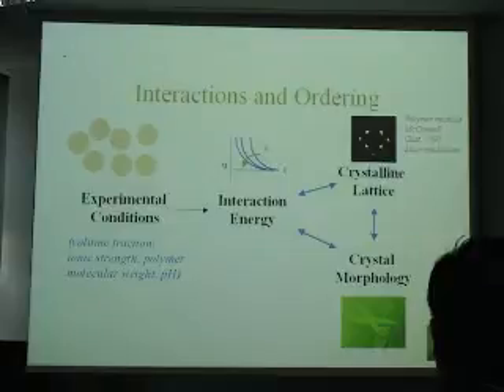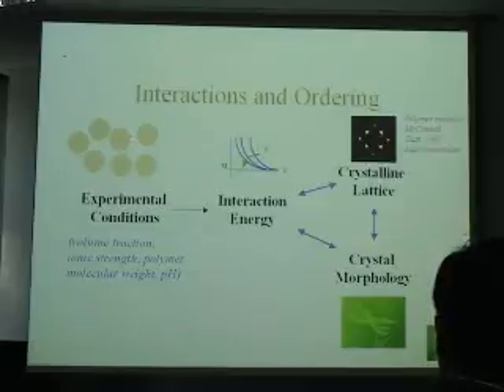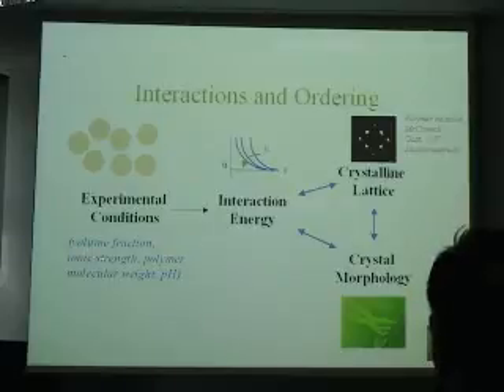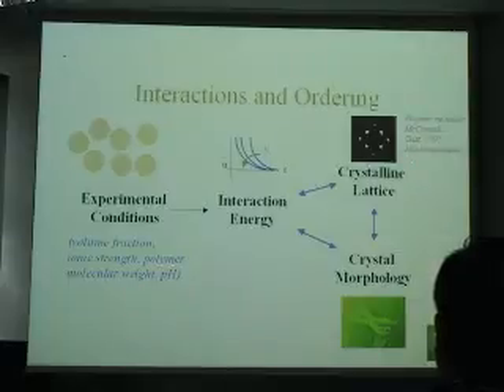Many of you may be familiar with colloidal crystals that have nice rainbow colors because the colloidal particles form an ordered array separated by several colloidal spacings, and they diffract visible light. What's nice about these systems as compared to molecular systems is that they have experimental conditions we can manipulate to cause this ordering transition. With a colloidal suspension, for instance, we can change the volume fraction of the particles and the ionic strength. If we have polymeric micelles, we can change the molecular weight of the polymers. In the protein case, we can change the pH.